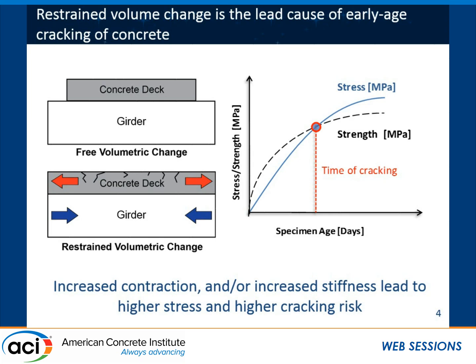In a very simplified, deterministic version, the dashed line shows the strength development in concrete, and the blue line shows the stress development. When the stress exceeds the strength, we have the cracking. There's been a lot of work looking at this in a non-deterministic way, looking at a statistical variation of both stress and strength and getting a window of cracking time or probability of cracking as opposed to a single time of cracking.